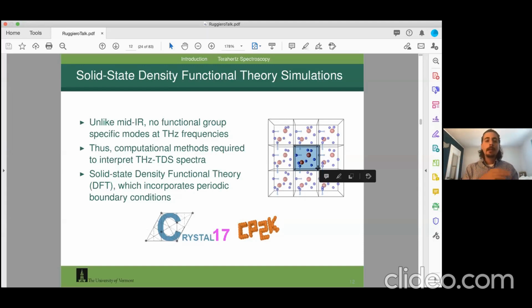The assumption in this case is that we have an infinite solid, which is a much, much better assumption than saying we have 10 unit cells, because these forces are very long range. They fall off in some cases as 1 over r or 1 over r squared, so very, very slowly. To do that, we use Crystal 17, which I helped develop, and CP2K. We do ab initio molecular dynamics. So we do this all quantum mechanically, all first principles, with very little to no empirical input. So all ab initio.